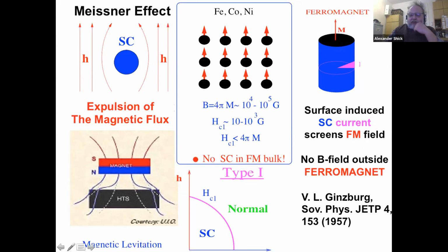Since that time it was already known that if you consider the phase diagram of the superconductor, here is the temperature, here is the field. If you are in the superconducting phase and apply the field, at some point, which is called the critical field, HC, superconductivity disappears. Indeed, you can think of the internal field due to the magnetic dipoles inside of the ferromagnetically ordered solid, and he did some simple estimates which gave him fields in the range of kilogauss to 100 kilogauss. And at that time it was already known that the critical fields are about 10 kilogauss. So the critical field is less than the internal field due to the magnetization. So the conclusion was that superconductivity just cannot survive the internal field due to the magnetic moments in the ferromagnets.